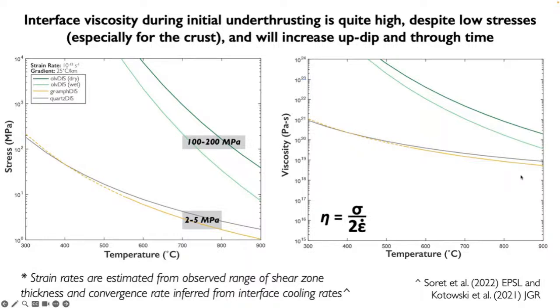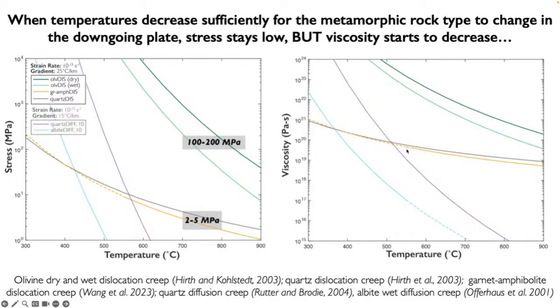The important thing now is that as you start to refrigerate the interface, as you start to cool it down by advecting cold lithosphere, the viscosity is going to increase a bit. It's not going to increase very much for the crustal rocks, but it's going to increase a lot for the mantle, to the point where it's going to be basically prohibitive to localize any more strain there. But you can continue to localize strain in the high temperature rocks until this garnet amphibolite is no longer metamorphically stable. At that point, what's going to happen is the low temperature sole is going to form.